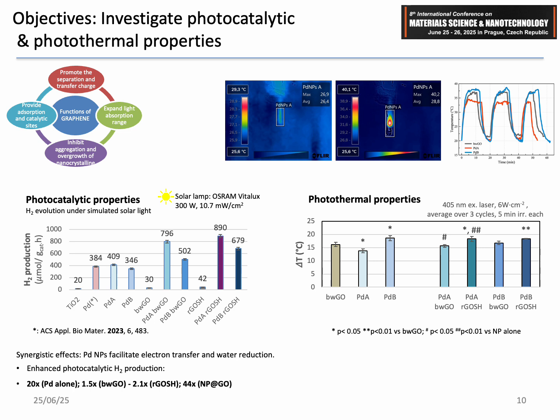Also, the graphene's high surface area enhanced the proton adsorption via electrostatic interactions, increased the local reactant concentration, and accelerated the photocatalytic H2 evolution, a process which involves 3 steps. First, light absorption to generate electron-hole pairs, then the charge separation and migration, and the water splitting at the surface of the nanoparticle. So single semiconductors struggle with the rapid electron-hole recombination, which limits their efficiency. And here instead we can see a clear synergy, with palladium alone giving 20 times enhancement over titania, and palladium GO hybrids reaching a 44 times enhancement, showing a strong combined effect beyond the single components alone.